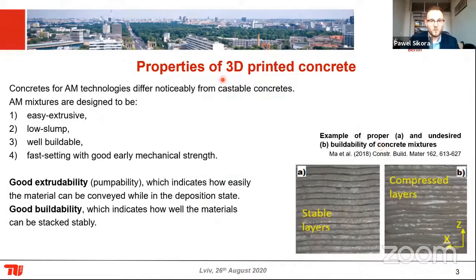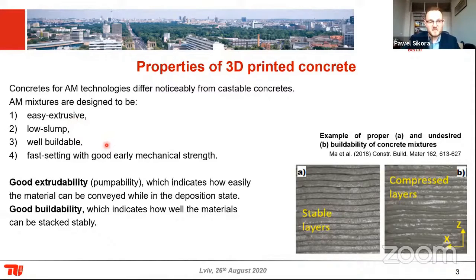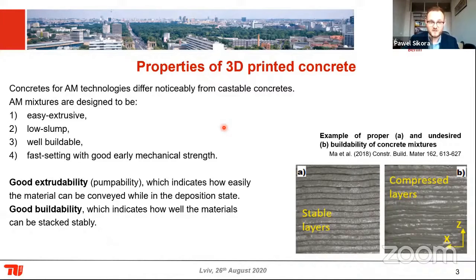What is the difference between 3D printed concrete and normal concrete? Although they both consist of cement, they are different materials with different properties. They should be easily extrudable — we need good pumpability. They should have low slump, meaning the material is not flowing and is stable. They should be well buildable, so we can place each layer on top of the previous one and avoid compressed layers. And since this is 3D printed concrete, it should have fast setting and very good early mechanical strength, as the layer-building process is very fast.